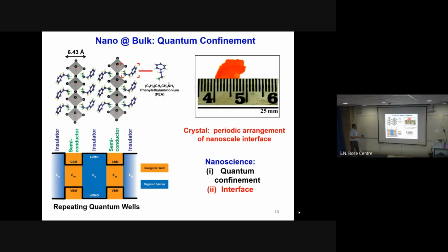Now in this kind of system, the properties that I'm talking about are mainly of single crystals. Big single crystals, say centimeter size in lateral dimension, thickness-wise about 0.5 millimeter. What's the separation between two layers? This will be something like 6.5 angstrom. I can change it. This will be something like 7, 8, 9, 10 angstrom in that range.